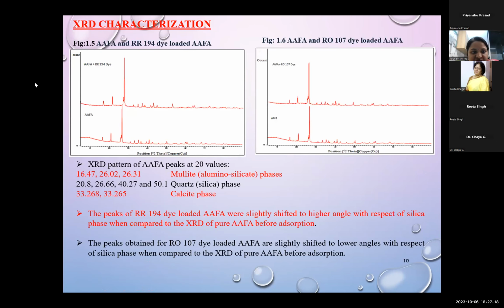XRD characterization. From the XRD characterization for both the dyes, we observed that the peaks of reactive red 194 dye loaded AAFA were slightly shifted towards a higher angle with respect to the silica phase when compared to the XRD of pure AAFA before adsorption. And the peaks obtained for reactive orange 107 dye loaded AAFA are slightly shifted to a lower angle with reference to the silica phase when compared to the XRD of pure AAFA before adsorption.